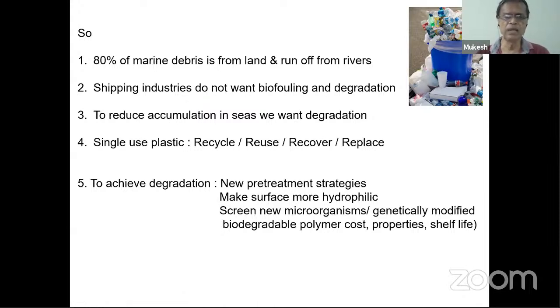If you want to prevent accumulation in seas, we want material to degrade. And as I showed, 80% of marine debris is from land. That and predominantly, as it is well known, that the plastic waste that's ending up in the rivers are mostly single-use plastics. So single-use plastic, one has to think about recycle, reuse, recover, and replace. And if you want to achieve degradation, we have to think about new pre-treatment strategies. I showed you about blending of polymers. I showed you about heat treatment, and then I also showed you about hydrophilic hydrophobic balance, coating the surfaces with the silanes and so on actually.